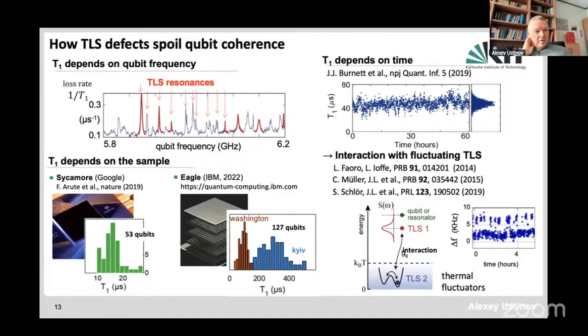And here you see on the left some data for a Google device some years ago, and more recent data for an IBM device with 127 qubits. You see such a large spread of relaxation time for the qubits fabricated nominally identically on the same substrate. Now, if you measure the T1 time of a specific device, you also find that it's not really stable. It fluctuates on the time scale of minutes to hours and even days. These fluctuations are actually of the order of the relaxation time itself.